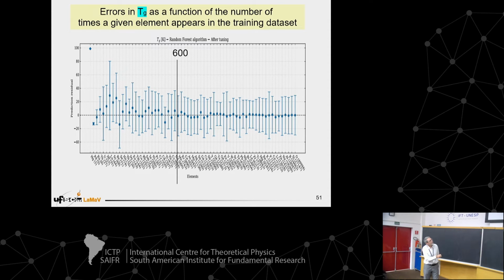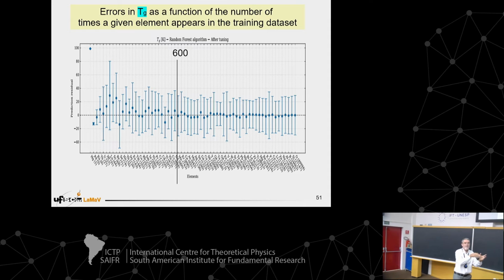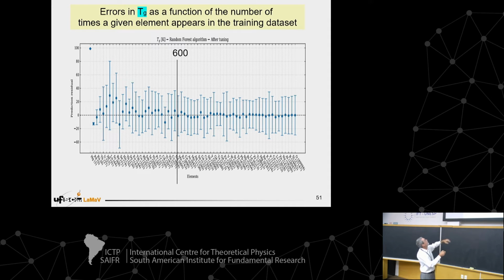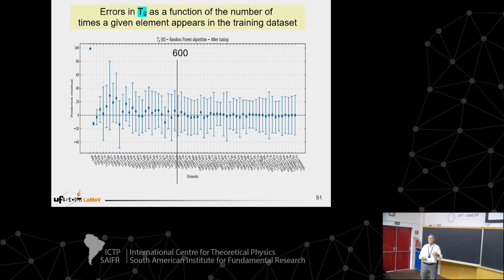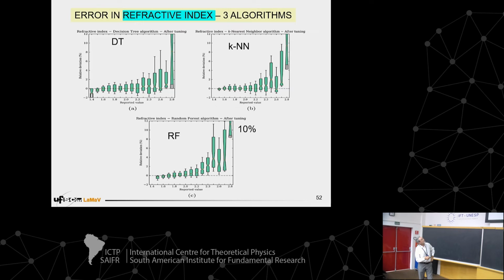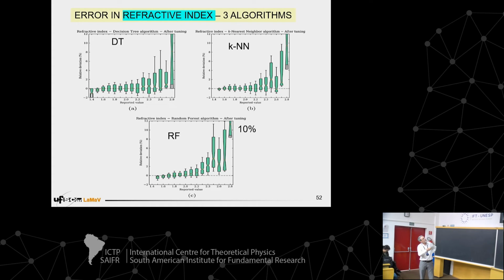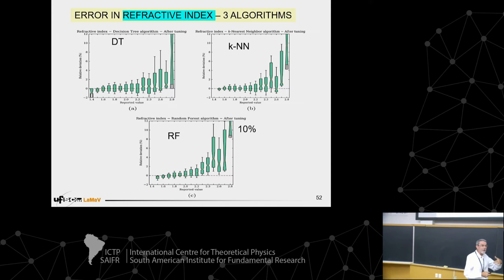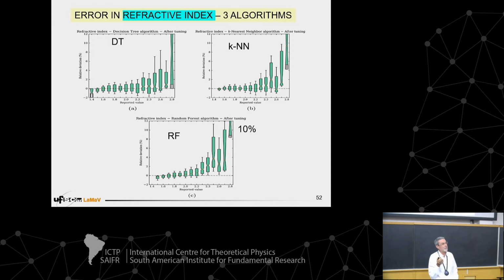This is zero. So the error is very, very small, but you need at least 600 compositions containing that particular element for this particular property, still TG, to have a decent prediction ability. These are other properties. Refractive index can do the same thing for the refractive index of the glasses, the same pattern. When you go to very high values of refractive index, 2.6 or very, very high values, the prediction ability becomes poorer and poorer because of the poor training. There are very few glasses with such a high value of refractive index.